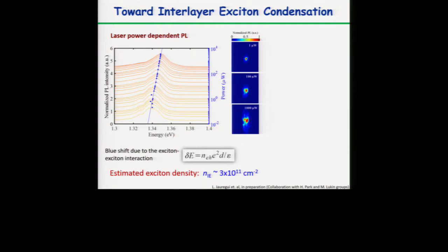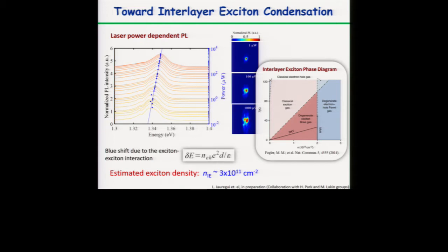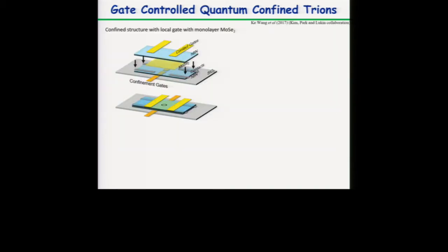Professor Westerveld asked me about this theory paper where they give an interlayer exciton phase diagram in TMDCs, and they claim that since the binding energy is large, we could probably obtain Bose-Einstein condensates of interlayer excitons in TMDCs at larger temperatures than in gallium arsenide, mainly because the binding energy is large, so we can push them to higher temperatures. They give what the BKT temperature would be for this BEC, for the degenerate exciton gas. So far, we're around here, but we still need to do more experiments to see if we can obtain any of these condensates.